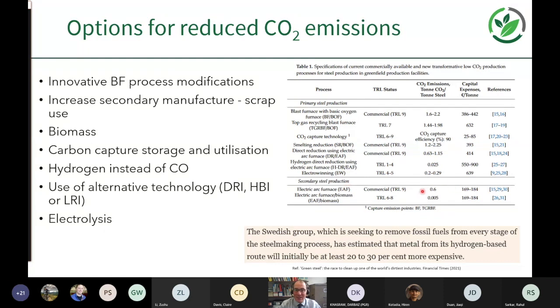So it's possible even with primary steel production to bring those emissions down. With secondary steel production, there's already significant opportunity to utilize those savings. And so we're talking about, in the blast furnace, these innovative process modifications: top gas, oxygen, high oxygen, etc. If we increase the secondary manufacture from scrap use, then we've got associated emissions reductions with that. Biomass, carbon capture, hydrogen instead of carbon monoxide as a reductant, and the use of alternative technology: direct reduced iron, hot briquetted iron, or low reduced iron as well. Or even electrolysis from molten iron oxide salts.